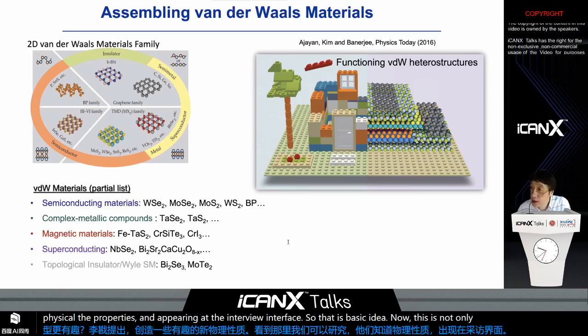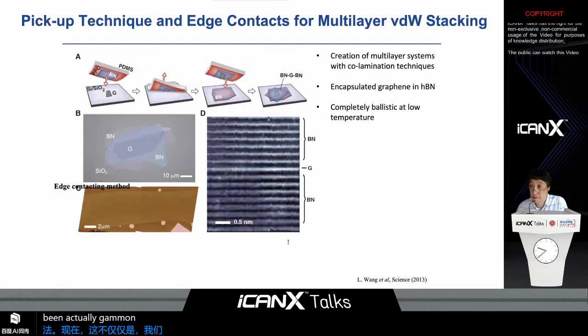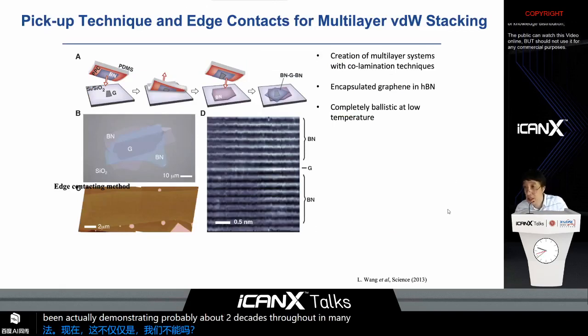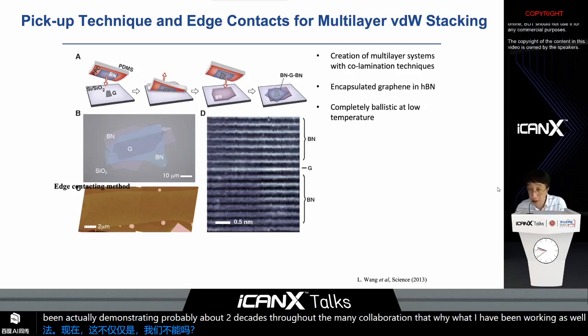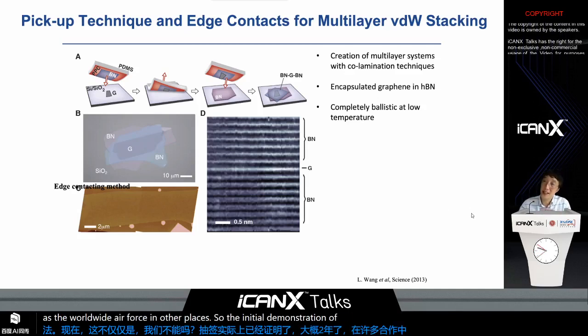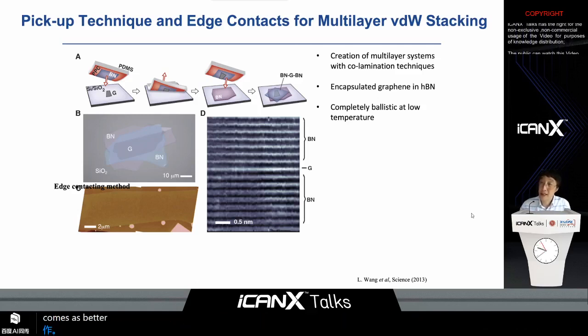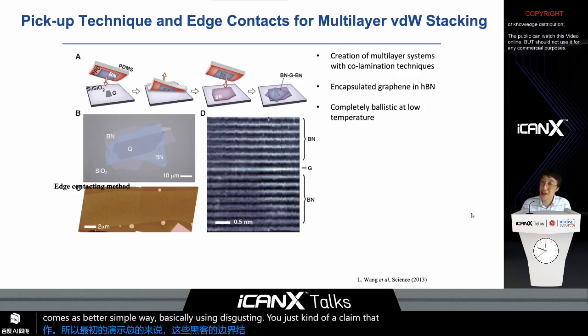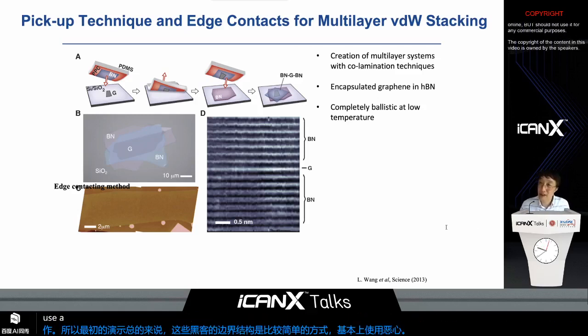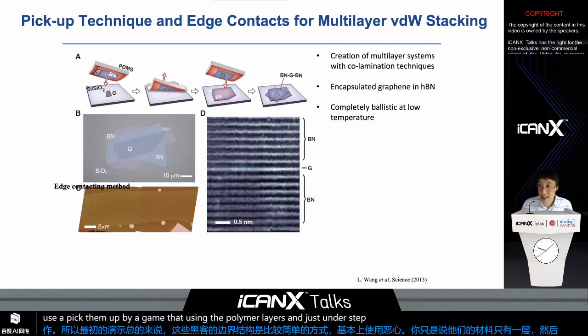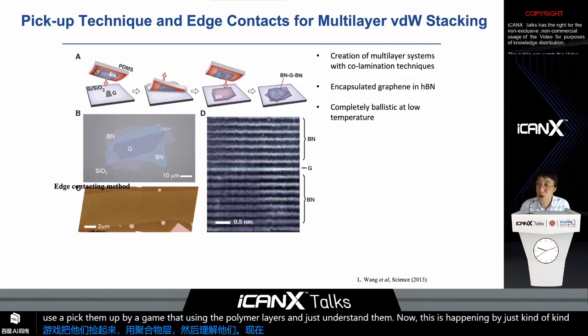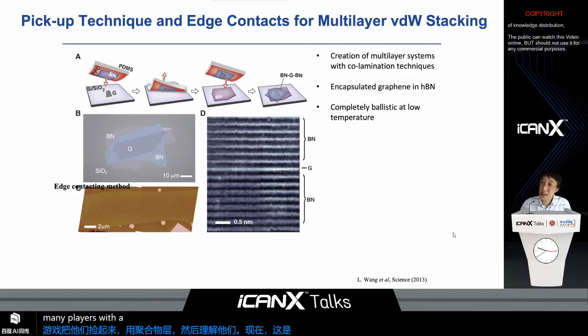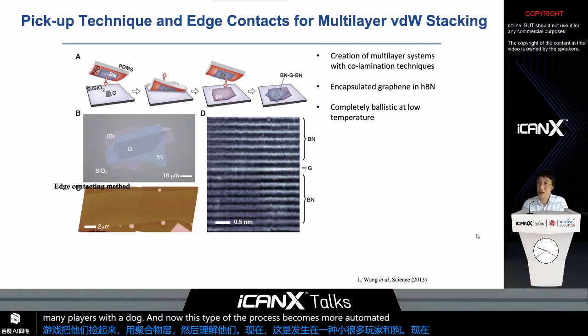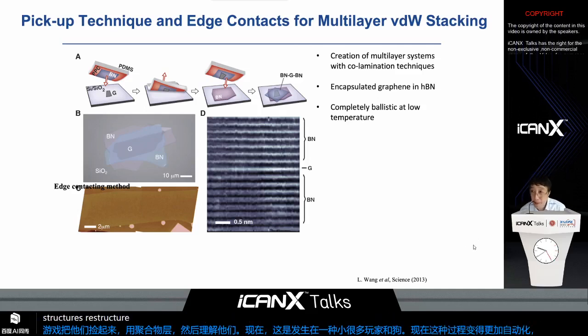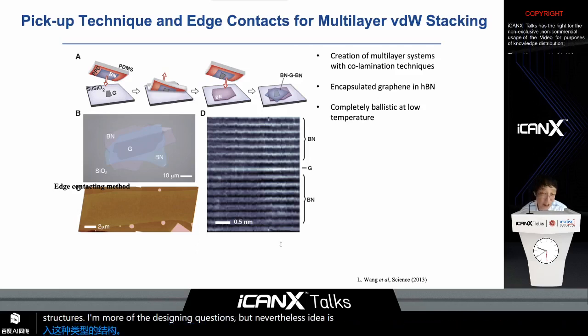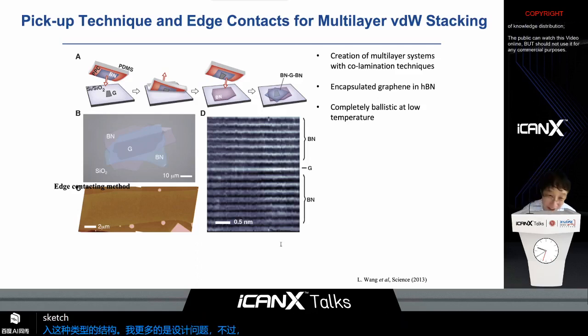Now, this is not only a cartoon we can draw; it has actually been demonstrated over the past decades through many collaborations that I have been involved in, as well as worldwide efforts elsewhere. The initial demonstration of heterostructuring van der Waals materials came in a very simple way. Basically, using scotch tape, you cleave the materials off down to a single atomic layer, then pick them up using polymer layers and stack them. This happens with small manipulators with the aid of hands. This process has become more automated, and one can now even produce these heterostructures by design. But the idea was already captured in the very initial work, just using scotch tape and manually stacking them together.